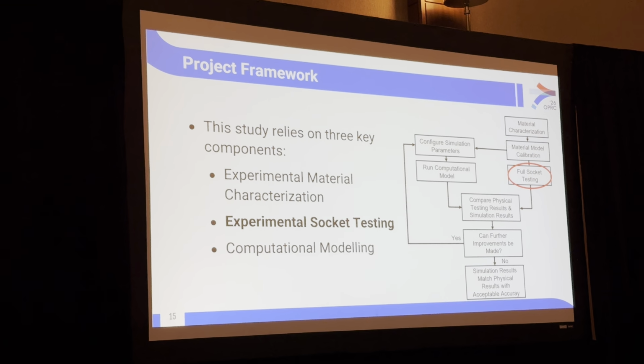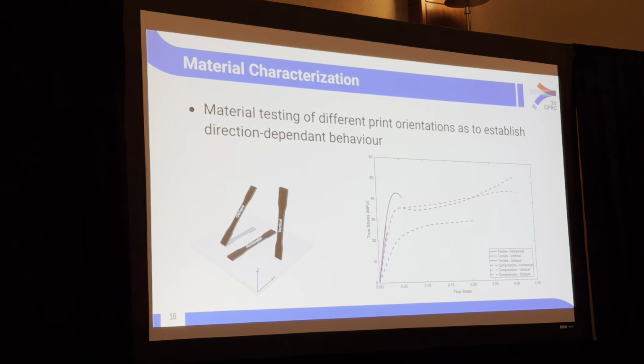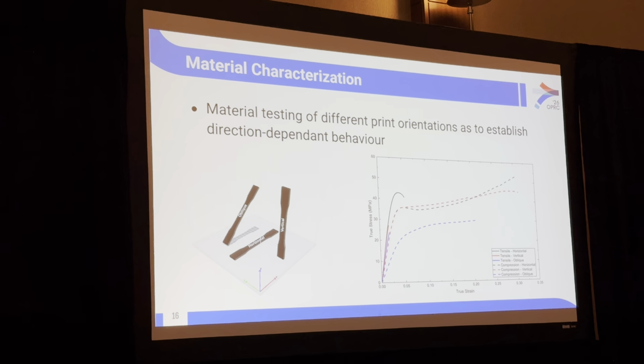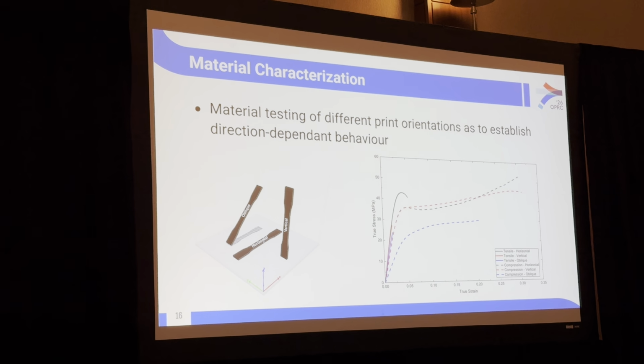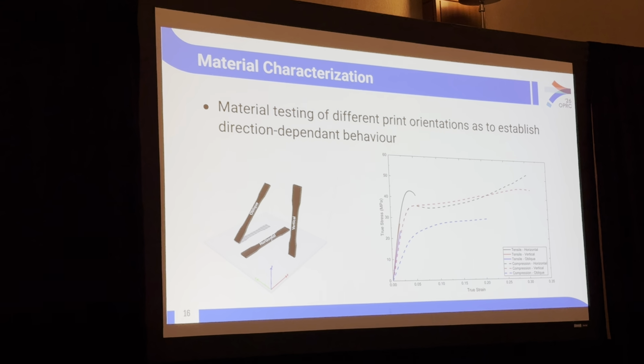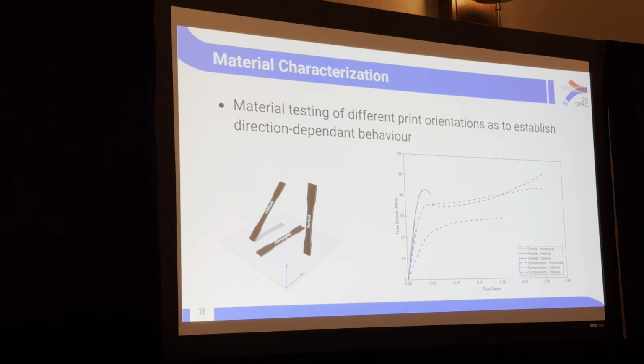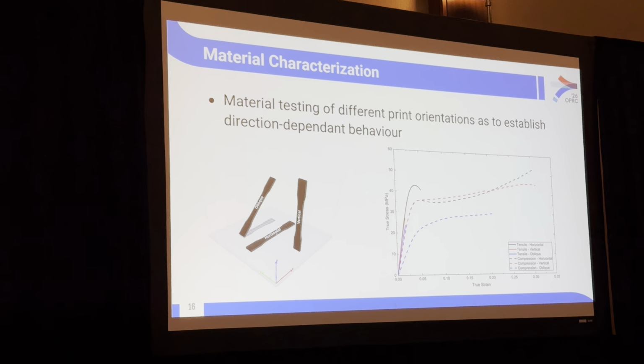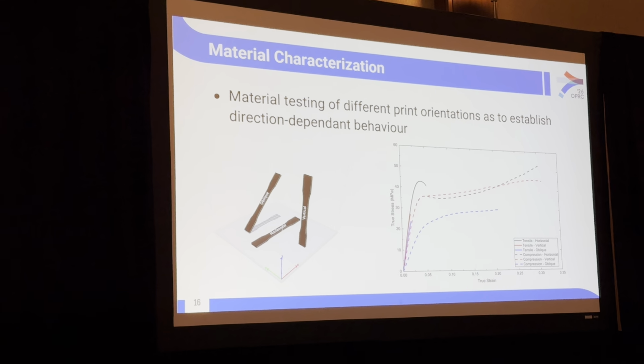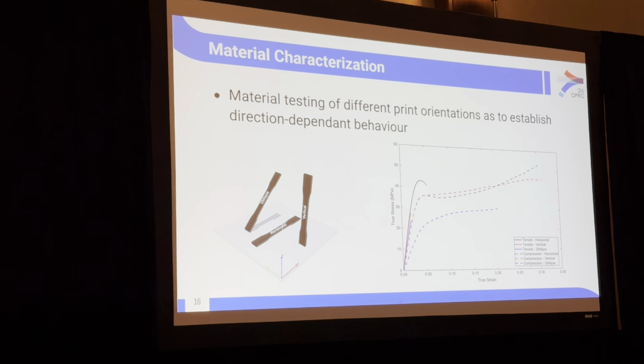the model development, and then used the data from our material test and our socket test to inform and validate that computational model. So touching a bit on our material characterization test, we performed tensile and compressive test of 3 different orientations of material samples. A horizontal sample, which was printed flat to the build plate, a vertical sample printed perpendicular to the build plate, and an oblique sample printed at a 45-degree angle.